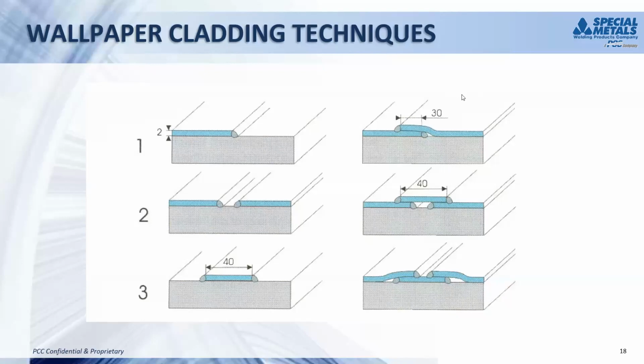The next two scenarios show how a batten strip can be used to cover the diluted welds. In the number 2 technique, you can see 2 sheets are welded to the steel substrate. Those welds would be diluted, but then a batten strip of the same alloy is welded over top of those welds, and those service welds would not be diluted. The situation number 3 is just basically the opposite of that, where the batten strip itself is welded to the steel substrate. And then the next 2 sheets overlap the batten strip, and those welds again would be not diluted.